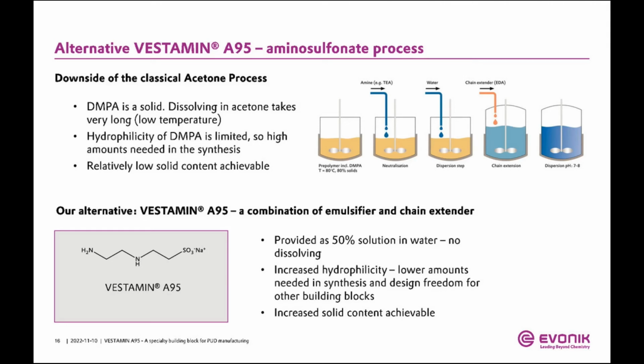That means that, if I really do it in a controlled way, they are turned into amine and then react again. So the decomposed isocyanate is turned into the amine, and the amine then reacts with another isocyanate, kind of using a mechanism of a moisture cure, if you wish. This can be done with PUDs also, but again, this is not affected by the kind of emulsifier you use. I don't see a big effect of the emulsifier in this case. It works with both DMPA and A95.